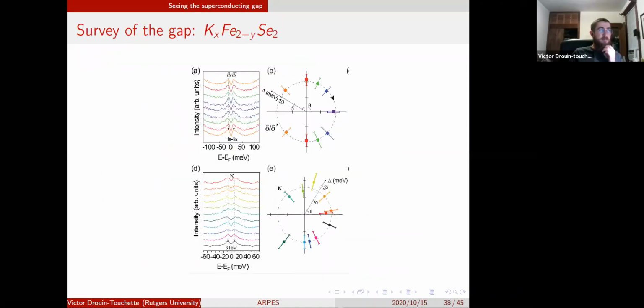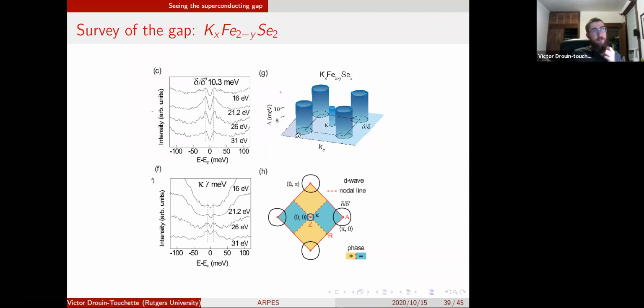How about iron-based superconductors? Oh yeah, iron-based are a mean bunch because they have a gap that is clear around the Fermi surface. So if you look at here, this is the momentum on the plane, right? These are all the Fermi pockets, and the height is the size of the gap. So the gap is very isotropic, and it's just there. You could say it's almost s-wave, but it's not electron phonon because the phonons are really small in most of them. In some, like in monolayer iron selenide, electron phonon might actually be the driver, but in many of them, it's probably not anything about electron phonon. So what is creating an isotropic gap is a big question. And some people like to think that they've solved it. I don't think anybody's solved the iron-based, and I don't think anybody's close to figuring out the iron-based.